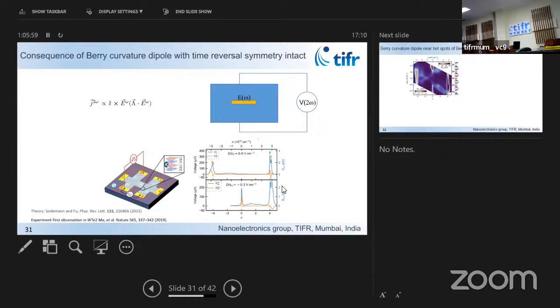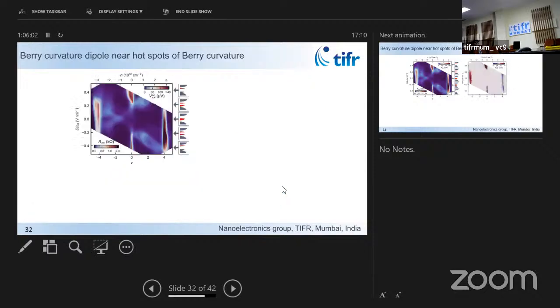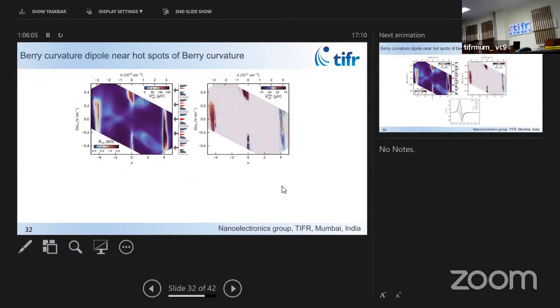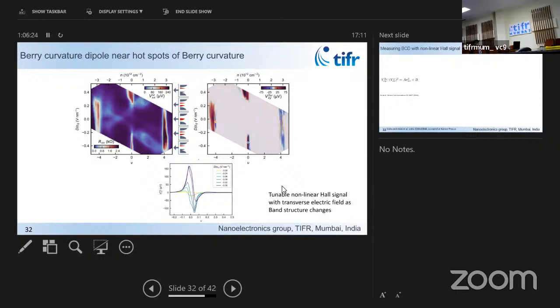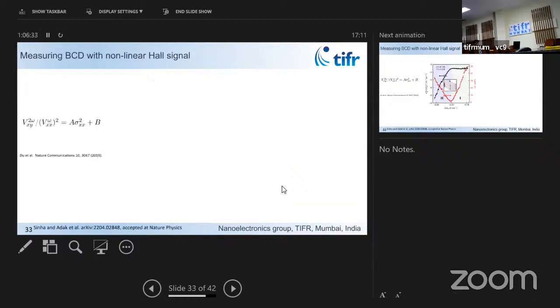So we can measure the nonlinear Hall signal as a function in the parameter space. So this is the resistance. Simultaneously, we can map the nonlinear Hall signal, and that's what we will use to extract Berry curvature dipoles. So this is how this nonlinear Hall signal is actually modified by electric field, because we have independent control. And so what one does is basically, when you apply electric field, you modify the Berry curvature distribution, and that as a result modifies this Berry curvature dipole. And the way to extract this Berry curvature dipole is to do this kind of a measurement.